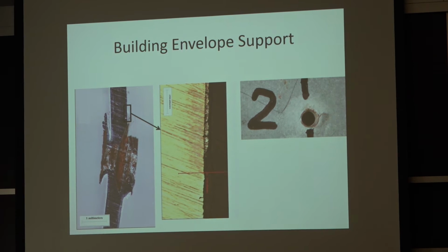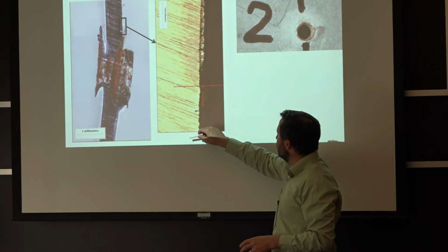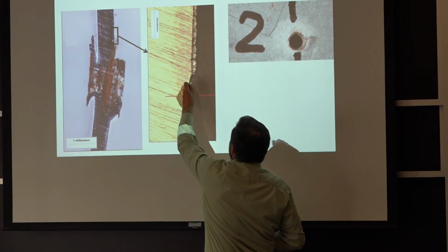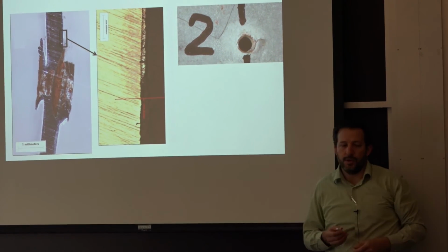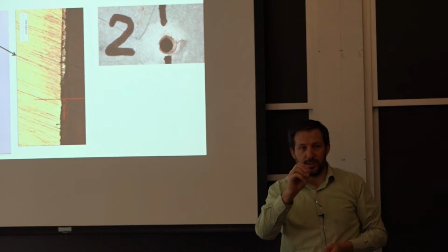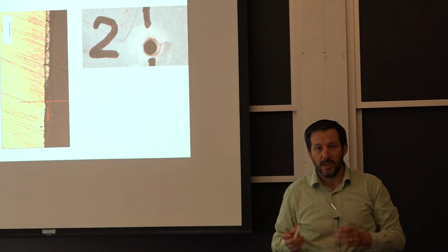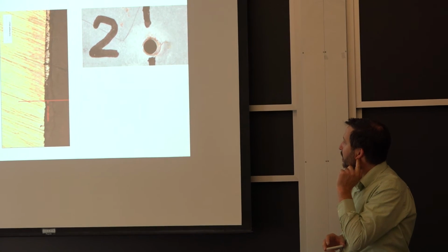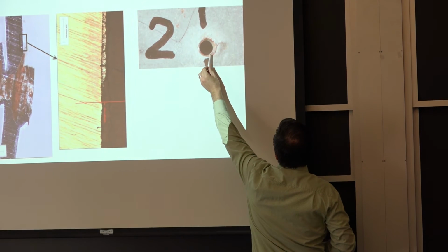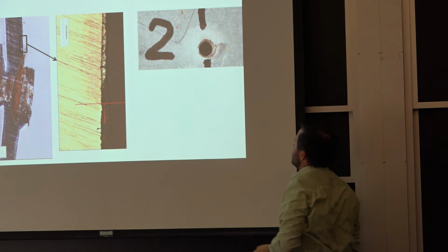So what happens is it's a moist environment. It's not completely submerged. And when that's the case, there's only so far from the hole. Let's say the hole ends here. You can go maybe up to about here, where you can consume the galvanizing. If you're further away, it's a little bit like a drop of water. A drop of water is only so big. So if you're talking about moisture, there's a distance beyond which you can't grab that extra sacrificial material to protect the hole. So we were getting into this regime where most of the holes were consumed in terms of the galvanizing up to about the size of the hole. So up to here, there really wasn't any galvanizing left. It was just the byproduct that you see there.